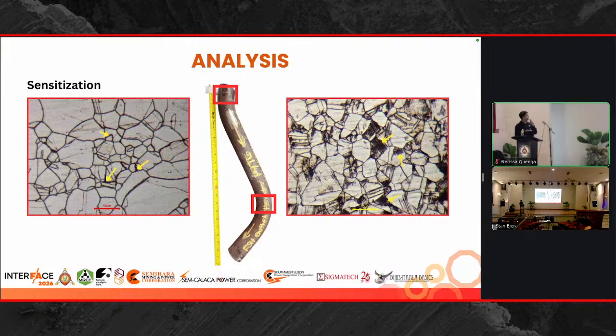And here at the bent part, since this bent part is cold worked, we have dislocation planes within the grain boundaries. Since these points of dislocations are high energy, the carbides can precipitate towards them. That's why there's sensitization happening within the grain boundaries as well. This is what we are trying to look at when we do microstructure analysis. So we can conclude that, of course, this part is already degrading.